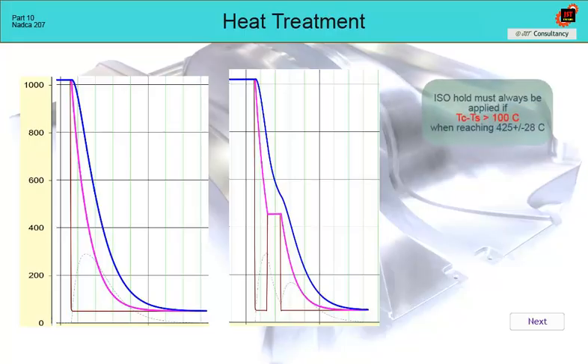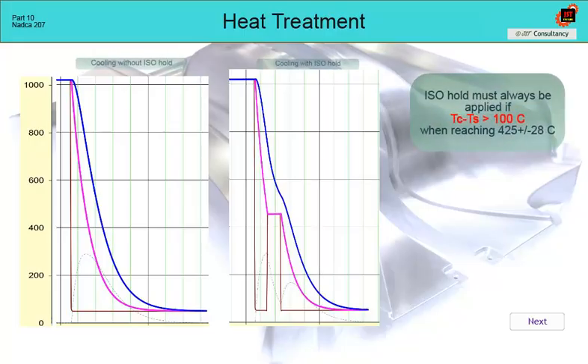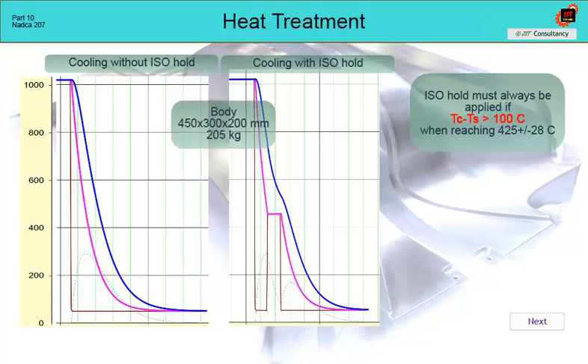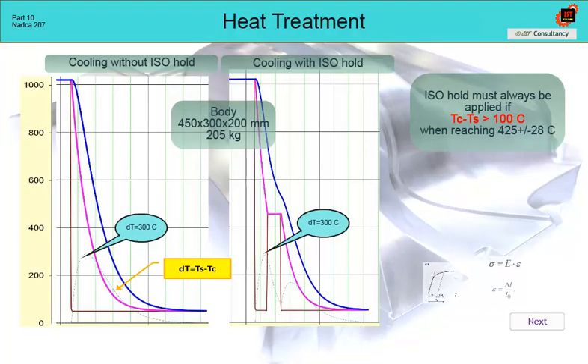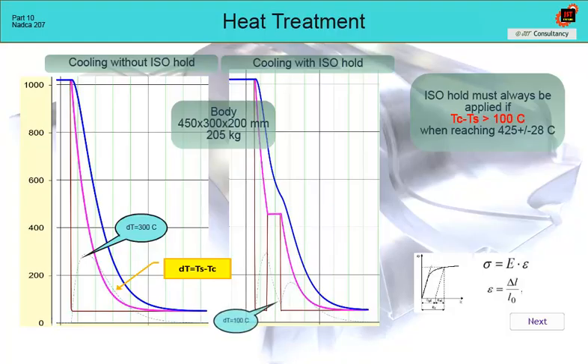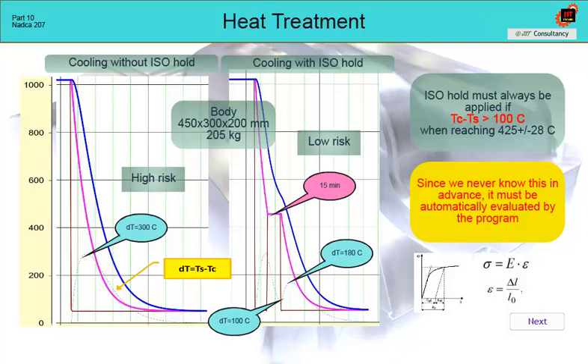The pictures show a comparison of cooling cycles without isothermal hold, and with isothermal hold for a piece weighing more than 200 kilograms. The result is quite obvious. There will be a significant reduction in the temperature difference between the surface and the core, and thus a reduction in stresses. Without isothermal hold, this temperature difference is 300 Celsius. After switching on ISO hold, the temperature difference drops to 100 Celsius within 15 minutes, and ISO hold is automatically terminated. Cooling continues with the next step. Subsequently, the temperature difference will rise again to 180 Celsius, but we have to live with that.